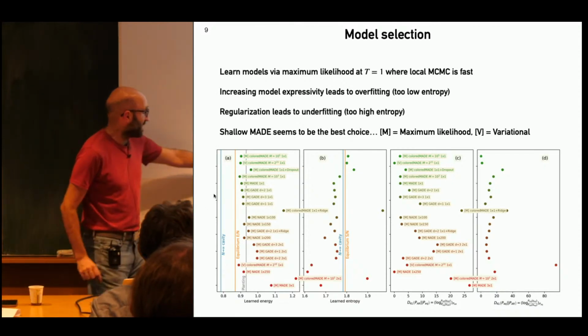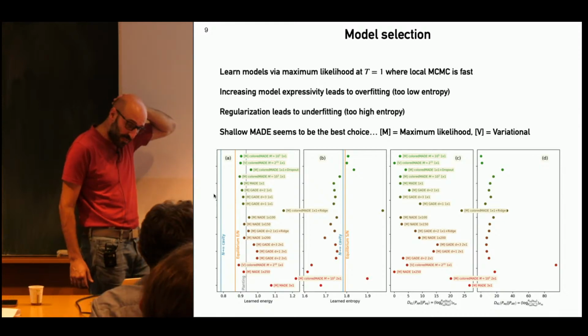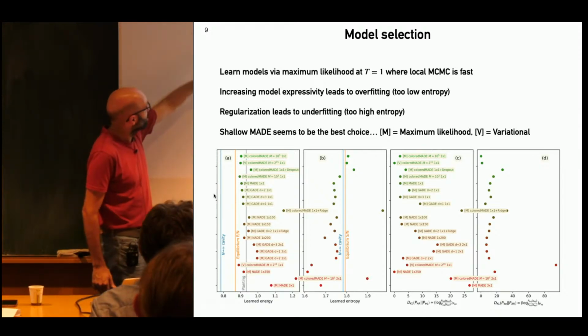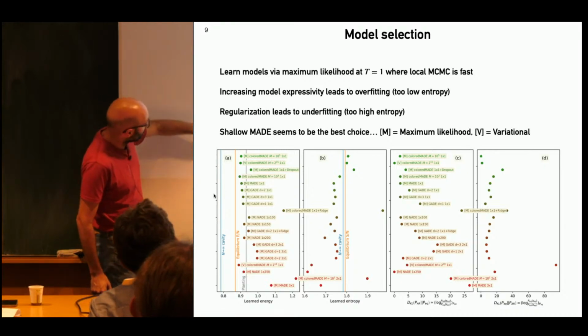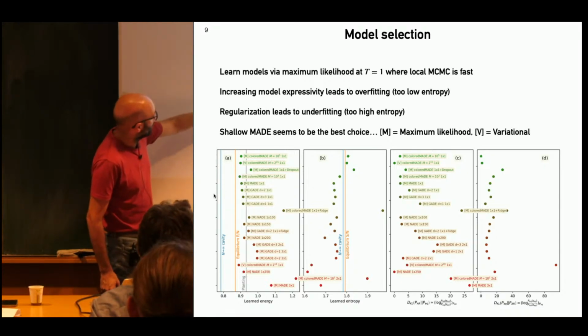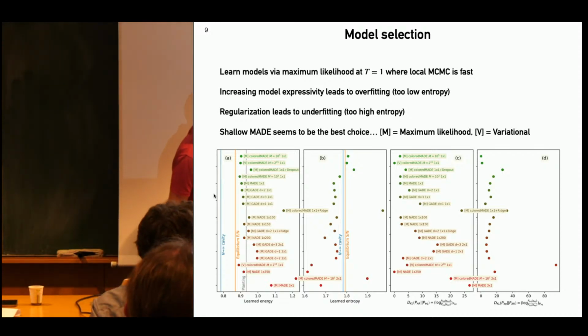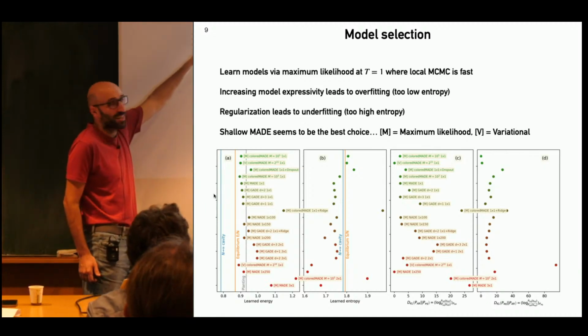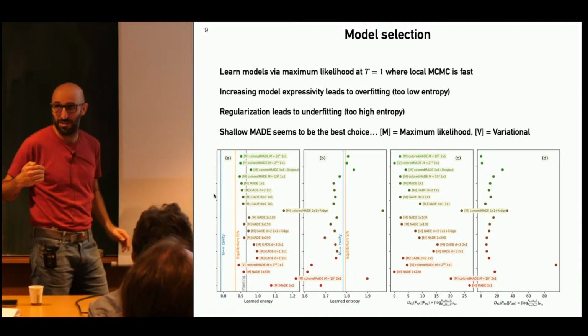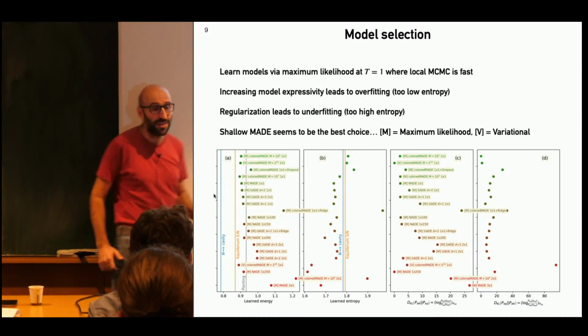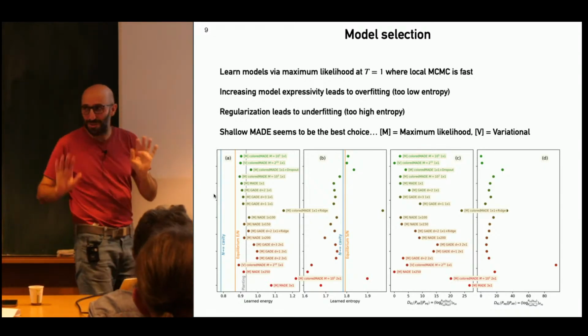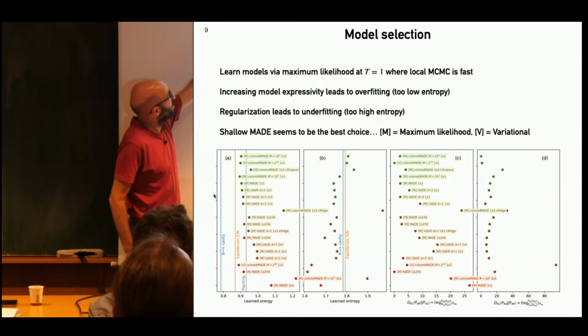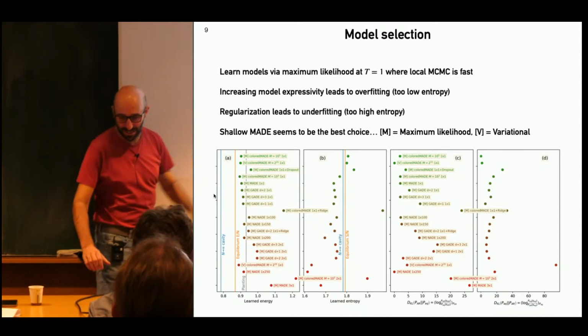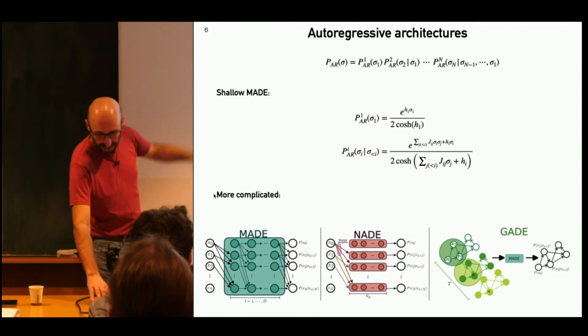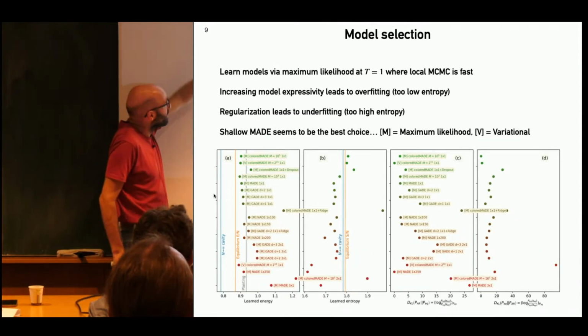What you see here is the energy. We trained these models by maximum likelihood on the sample that we have. What you see here are the energies: this is the equilibrium energy that you know, and these are the energies of the model. These are the entropies, and these are the Kullback-Leibler divergences. There is a lot of information; you don't need to look at all of it. The models are sorted from top to bottom in order of free energy. Free energy at temperature 1 is just energy minus entropy. The only important thing is that there are two models that are good. These are basically the shallow MADE, the one where you do this. So these seem to be the best models in the class that we tried.